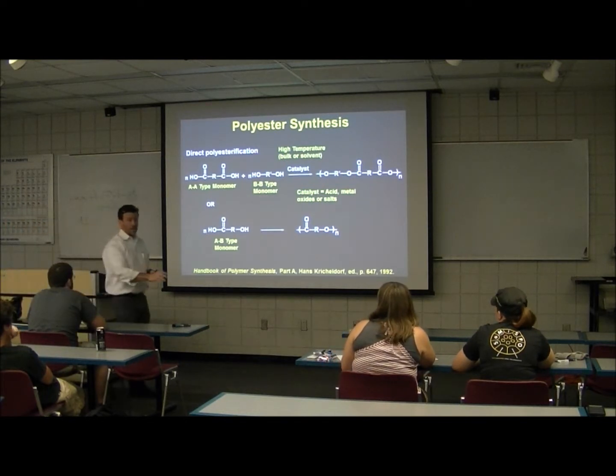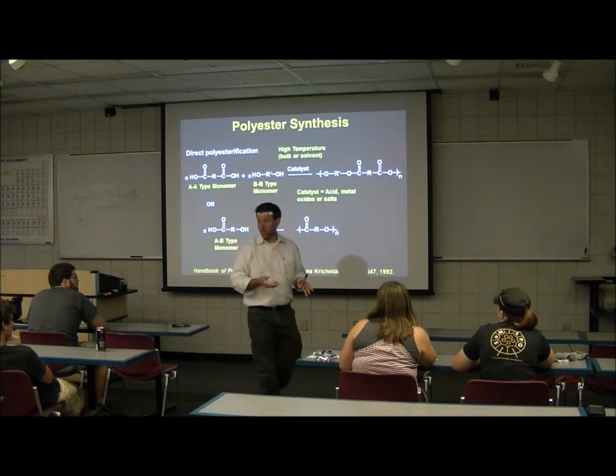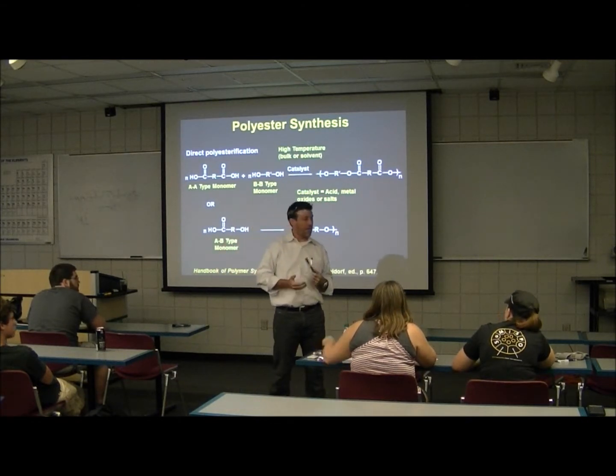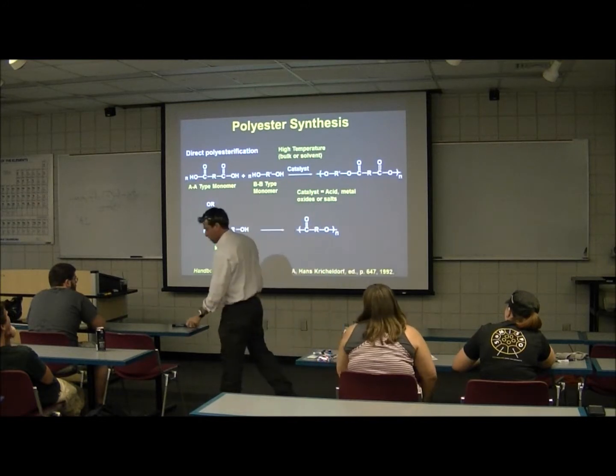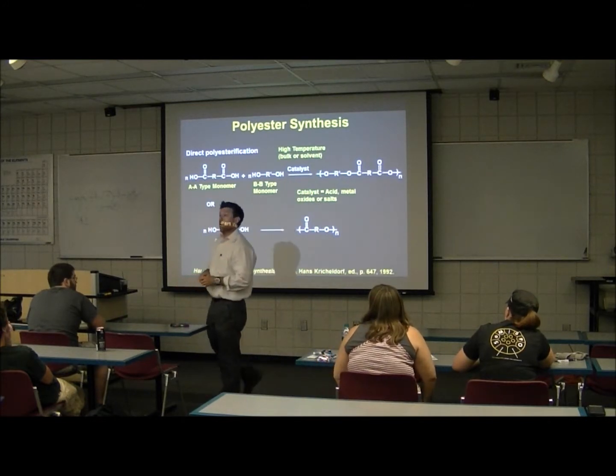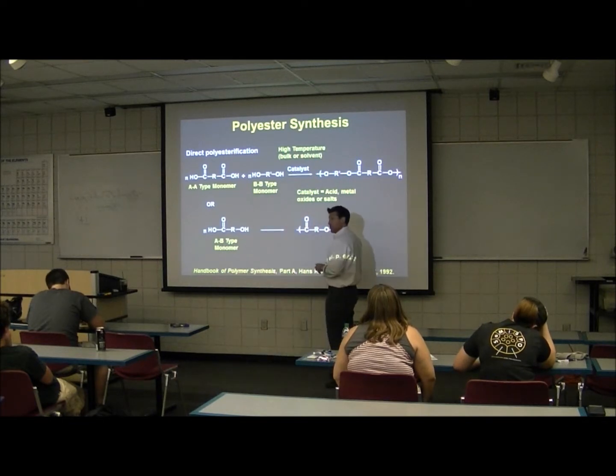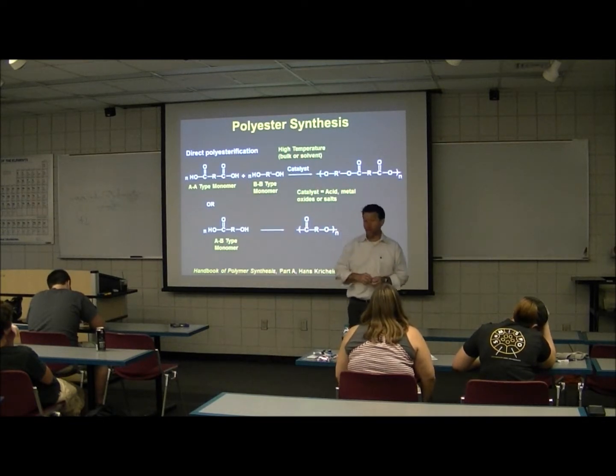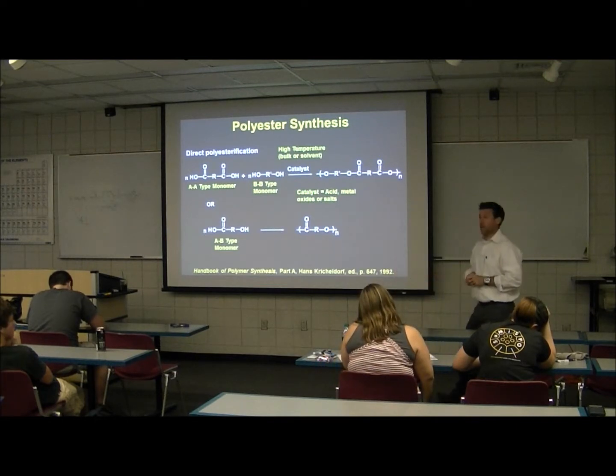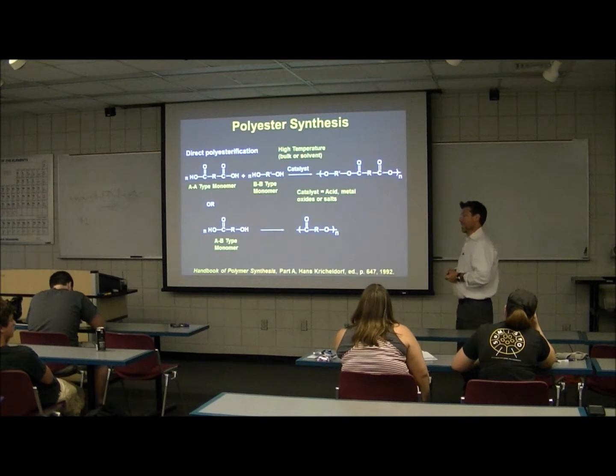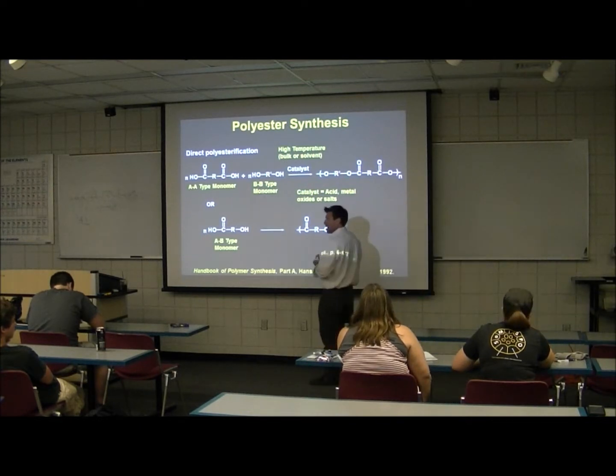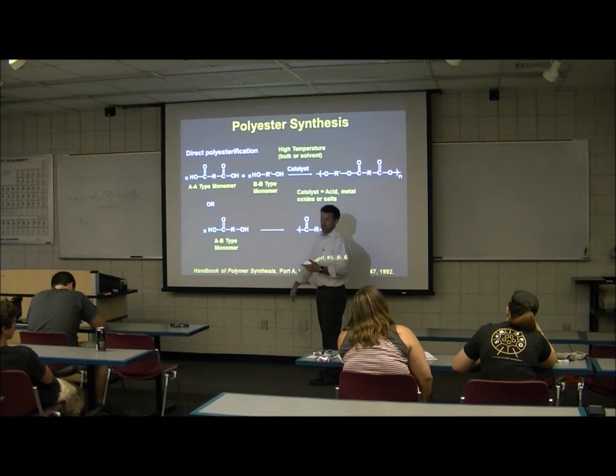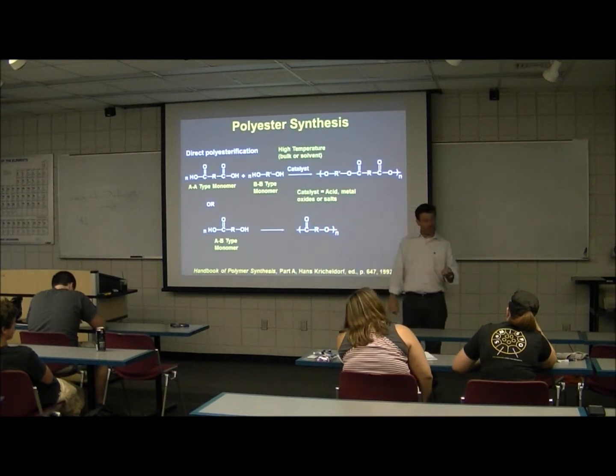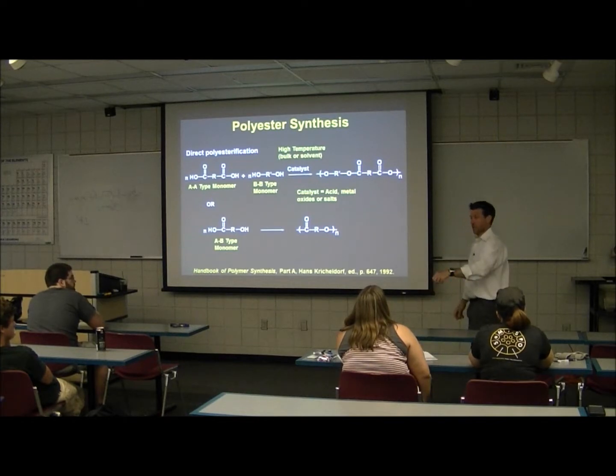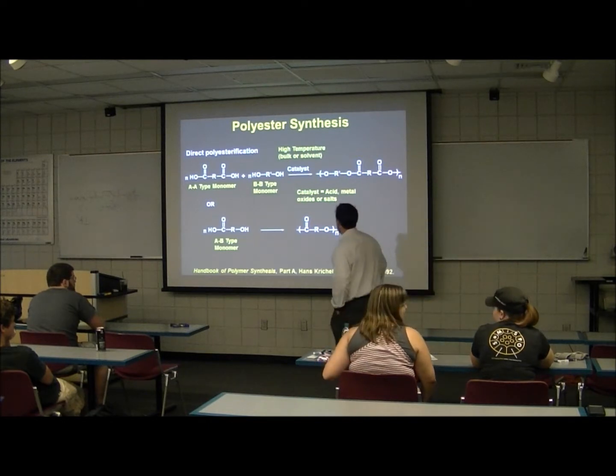So resins with a lot of color can't make pastels and light color unless they're yellow. People get tired of making yellow or buying yellow. So what was that color with it? Sulfuric acid as a catalyst. You'll actually start to get some sulfate adducts, and you'll get chromophores from that. Sometimes people have determined that those are parts of the aromatic ring, sometimes not. But sulfuric acid is an excellent catalyst for low temperature systems, but only in low doses. If you put too much in, you instantly get color. I don't know if you've ever played with sulfuric acid, but you can put it on almost any carbon compound. You just put a couple drops on a piece of wood and it will char it. So, just to get a feel for that color, the color bodying.